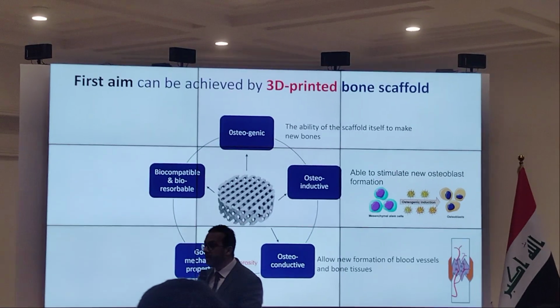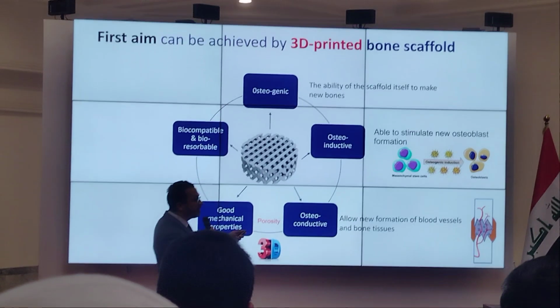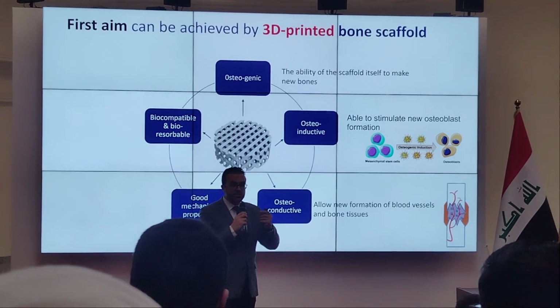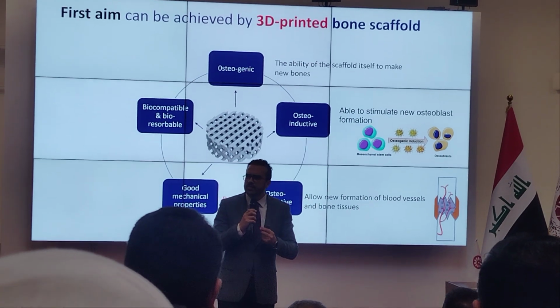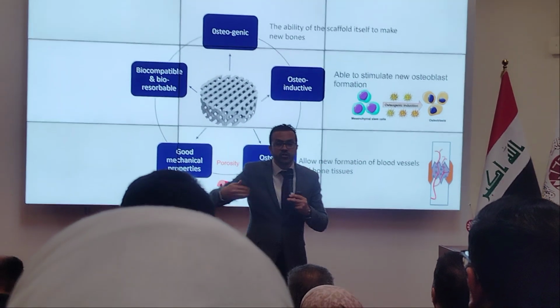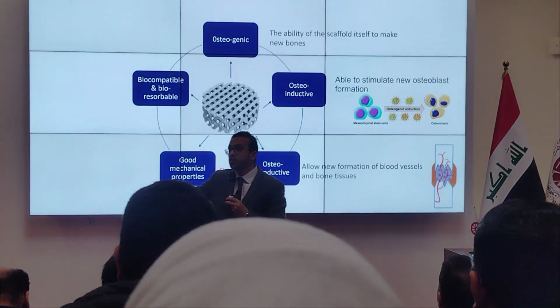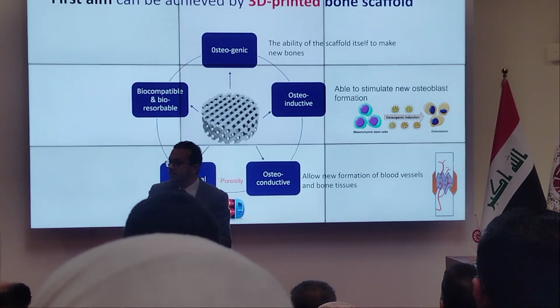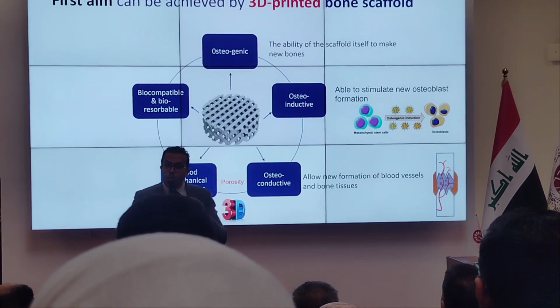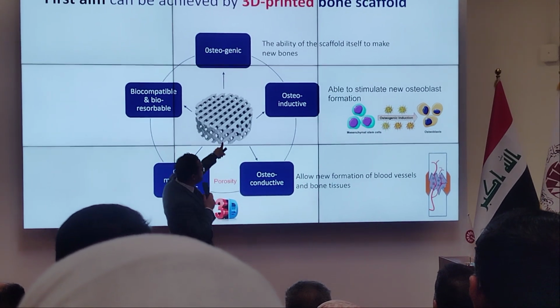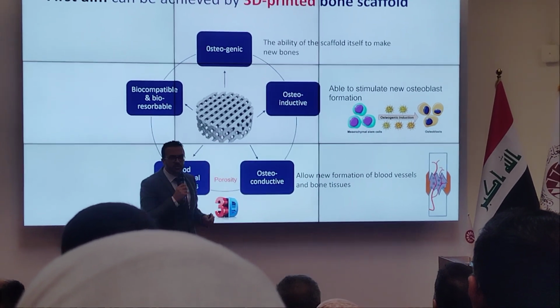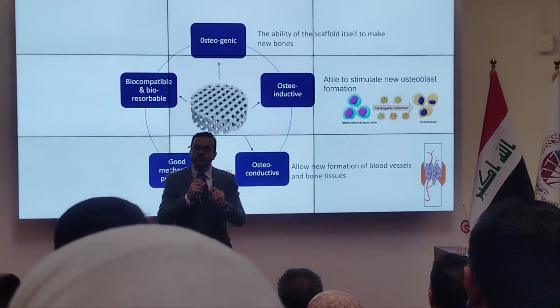Number two, this material is osteoinductive. The material itself is osteoinductive. What does this mean? It will induce the surrounding stem cells to differentiate and proliferate into osteoblasts, new bone cells. Number three, we can control the pores, the porosity of this scaffold. And this is the most important thing here.